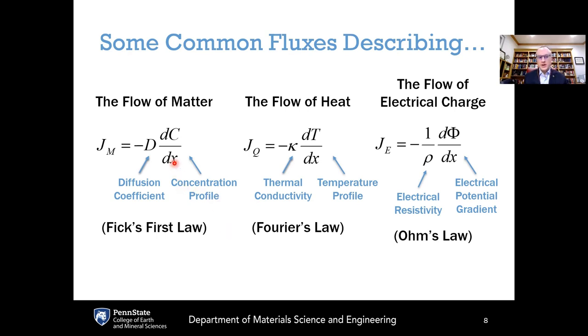This was Fick's first law, which governs the flow of matter, Fourier's law, which governs the flow of heat, and Ohm's law, which governs the flow of electrical charge. You'll note that all three of these equations are mathematically identical. They all have a flux that's equal to some sort of thermodynamic driving force, whether it is a temperature gradient, a concentration gradient, or an electrical potential gradient. That thermodynamic driving force is multiplied by a kinetic coefficient, either the diffusion coefficient, the thermal conductivity, or the electrical conductivity, or 1 over the electrical resistivity.